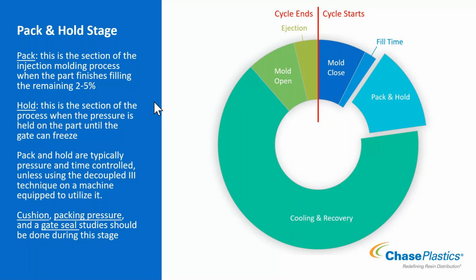This lets us keep everything in the tool. If we were to release pressure at that point in time without having a gate sealed off, you can get backflow out of the cavity, which will then introduce some quality issues. So pack and hold are typically pressure and time controlled. Pack has a velocity component and is pressure controlled. Hold is pressure controlled with no velocity component.